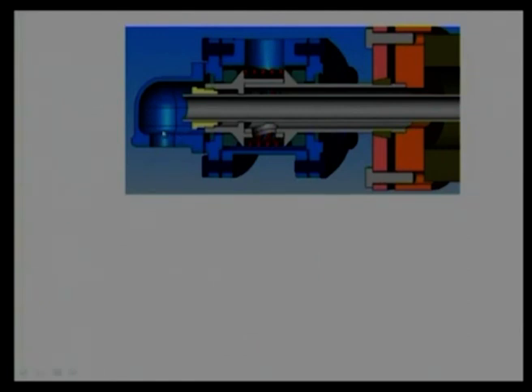You can say the steam goes in and tries to push these stainless steel shafts. There is one stationary joint, another rotating joint, and these are the seal rings. This is a radial kind of seal ring, and this is another seal ring which I showed in a previous slide. This is the seal ring we are talking about, where the wear happens. And if there is a leakage of steam, then there is a loss of the fluid that we require to stop. Now, if the seal ring is getting worn out, there is a spring over here which pushes the shaft against it. If the thickness of the seal ring is reduced, because we have already used a pre-compressed spring, it will adjust the position of the seal ring.